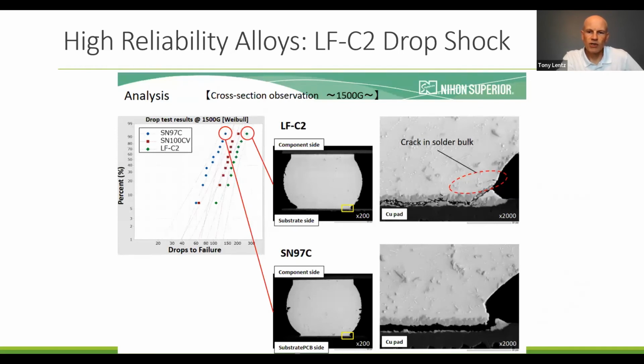Here's cross-sectional pictures of the failure modes. So LFC2 tended to fail in the solder bulk, and then SN97C tended to fail along the intermetallic layer, as you can see here in the cross-section.